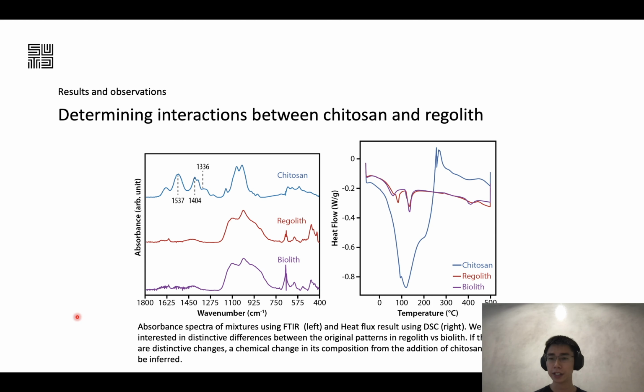Now the idea here is that in DSC, if there's a chemical reaction between chitosan and regolith, we would observe some shifting in the peaks of the heat flow patterns here. So the idea is that if there's a chemical reaction, some of the mineral phases will be consumed or changed, and this altered mineral composition will likely have a different temperature at which they change phase.